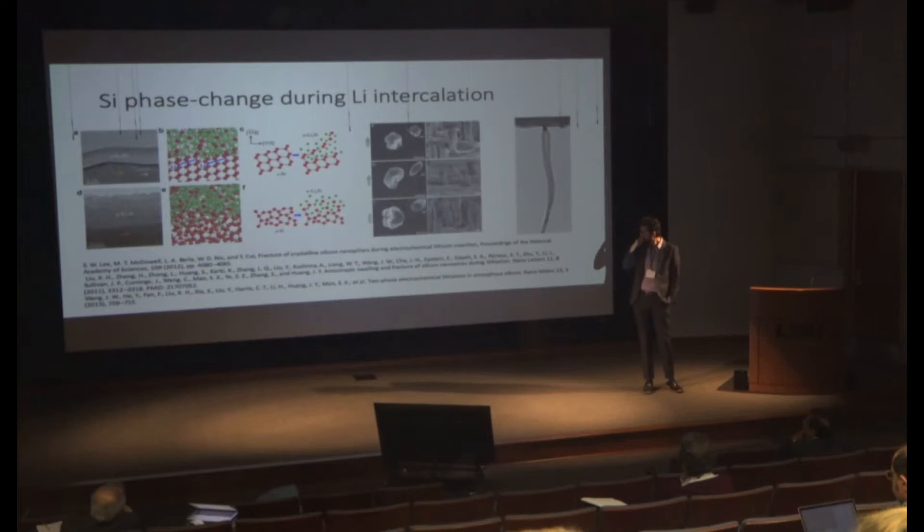The second thing people understood was that once these things phase change, or if you start from an amorphous sample, if you lithiate and delithiate it, the thing doesn't go back to its original form. So there is some sort of inelasticity going on.